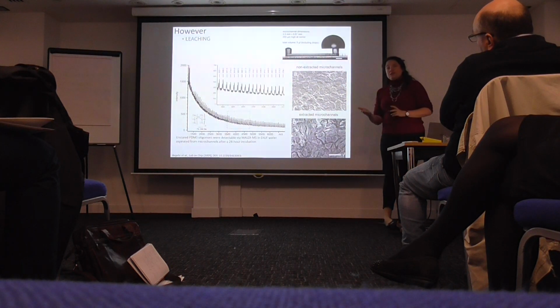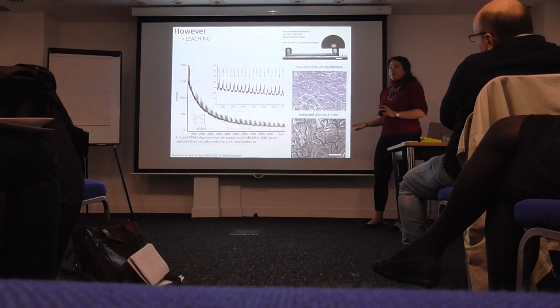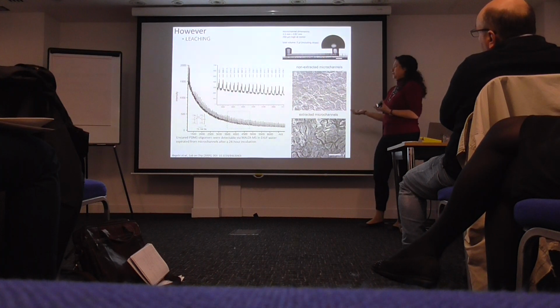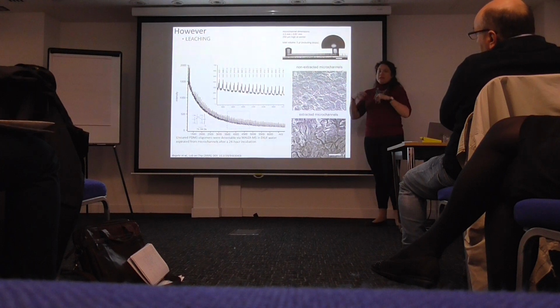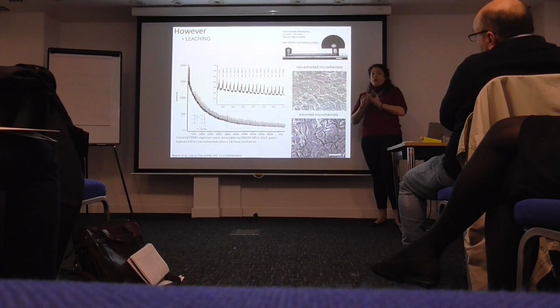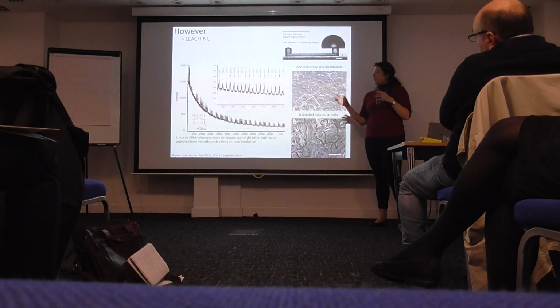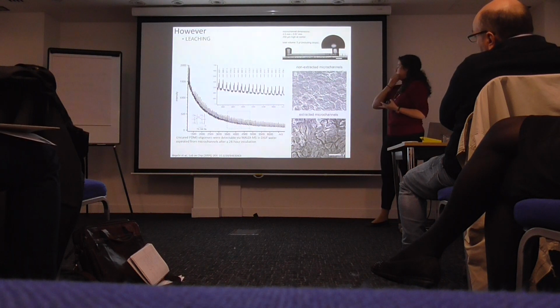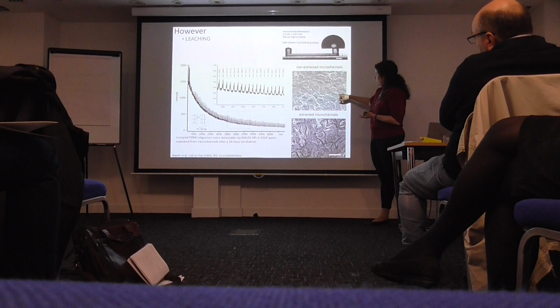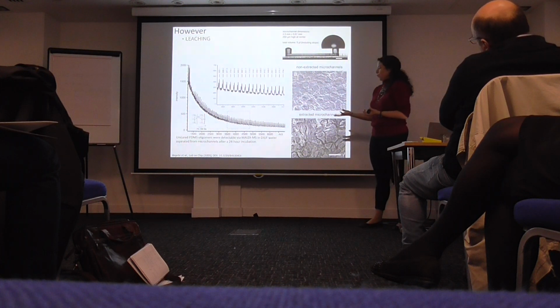One thing that's not as visible as the evaporation, because with evaporation you get gas bubbles and you clearly see it, is the fact that PDMS leaches. When you're mixing the two components together at a 10:1 ratio, not everything is cured. You still have monomers floating around, and they do make it to the surface. And if you actually pay attention and look for silicone monomers, you start seeing them accumulating inside of the membranes of your cells. And that's a really big problem.